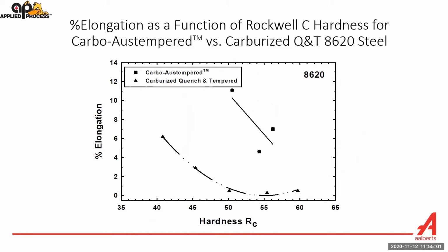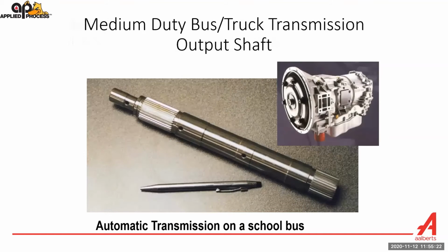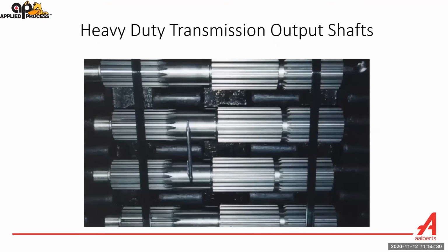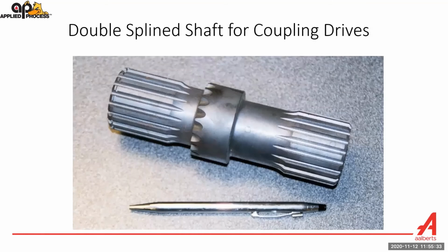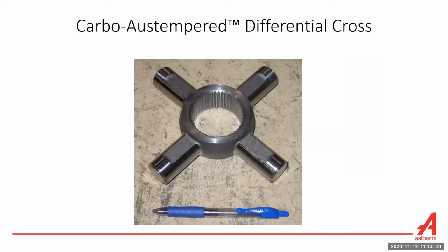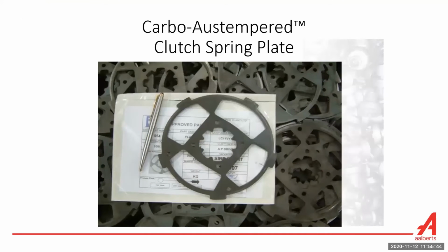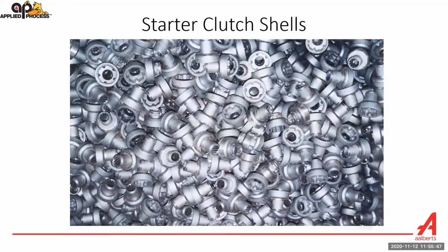This plots elongation versus Rockwell C hardness, and the carburized, quenched, and tempered is the curve with the triangles, and the squares is Carbo-Austempered. So what we have is, for higher hardnesses, we have higher percent elongation, which yields higher toughness. Examples where Carbo-Austempering has been used: output shafts on transmissions, another transmission output shaft, another spline shaft, a differential cross, clutch spring plates, starter clutch shells.